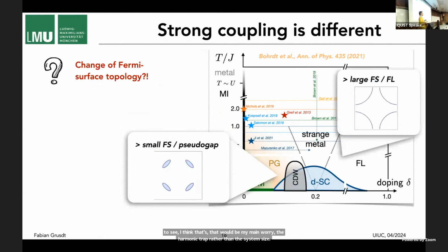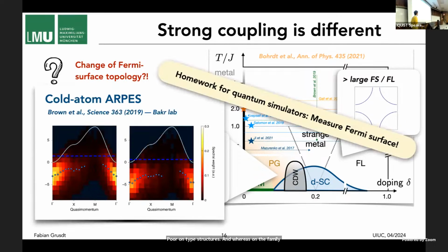Great. So another important property in solids that's known is that at low doping, we have a small Fermi surface. That's basically up to 20% doping. And that, again, matches what you expect from these magnetic polaron type structures. Whereas on the Fermi liquid side, beyond 20% doping, you get these large Fermi surfaces. So understanding that is, of course, a key quest. It's the subject of debate. How can we understand this transition from this antiferromagnetic regime here to that large Fermi surface regime?